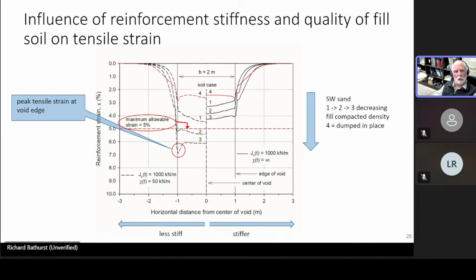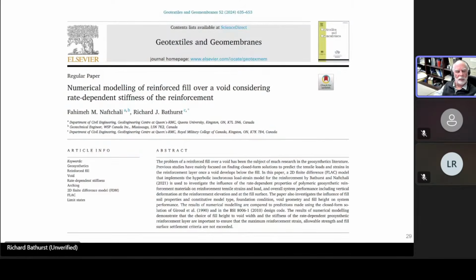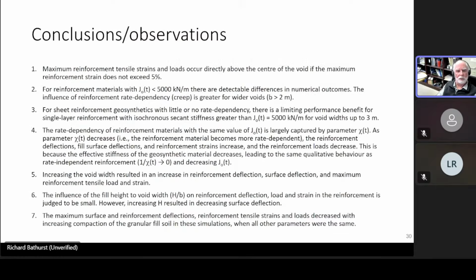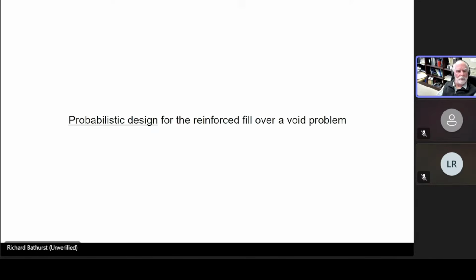So from this work, there was a paper that was published together. You can read this paper and get details. The paper records a number of important conclusions and observations. They're listed here. I'm not going to go through them in detail. Some of them I've mentioned already. For example, provided we have a reasonable width of void, the maximum strains should not exceed 5%. And as the void width increases, we get increasing reinforcement deflection, surface deflection, and maximum reinforcement tensile load and strain. So you can read this paper at your leisure.